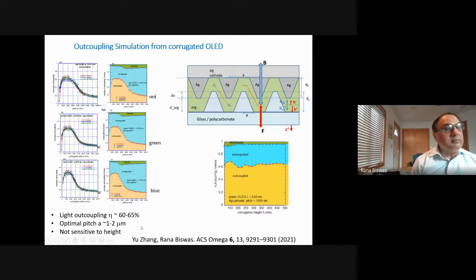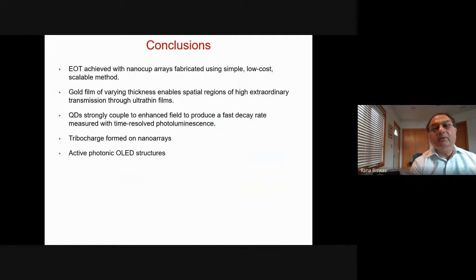And we have some experimental results which have just been published about a week ago, which concentrate more on this region in the middle that demonstrate outcoupling of the order of about 50% experimentally. So this is a very encouraging experimental result, and we hope to actually do even better with the experiment that would bring it closer to the theoretical prediction. So I think this might be a good time to conclude.